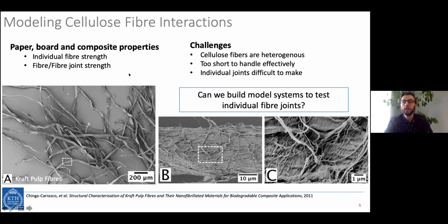And so the challenge that we're facing within this is that cellulose fibers are largely heterogeneous, and it can be difficult to handle them because they're relatively short. So if we look at some SEM images of pulp fibers, you can see that there's a lot of different hierarchical structure in here, and they're rather non-uniform.